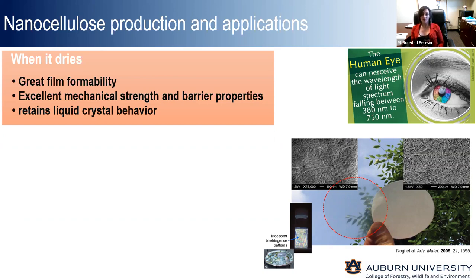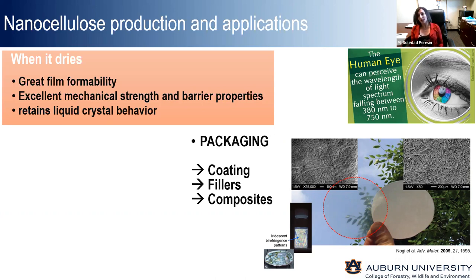So this material, because the fibrils are so small, does present excellent mechanical strength and barrier properties. And also, if we are talking about nanocrystalline cellulose, when the suspension dries, they will retain the liquid crystal behavior, and they will also have iridescent and birefringence patterns that we can play with to create certain domains and interactions with light to produce very colorful films. As for these applications, of course, packaging is one very appealing application. We can think about nanofibrillated cellulose for coatings, as well as fillers, and also in the composite industry.